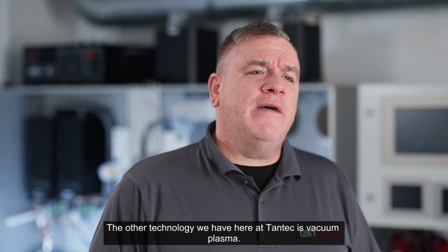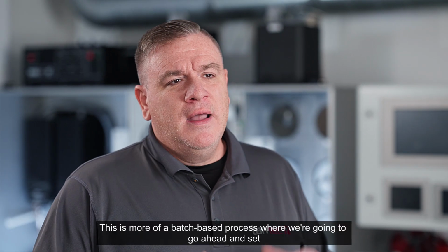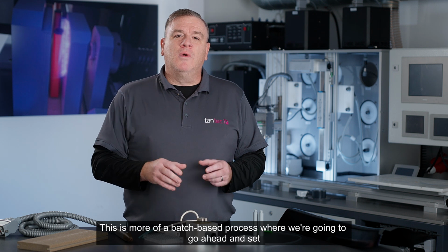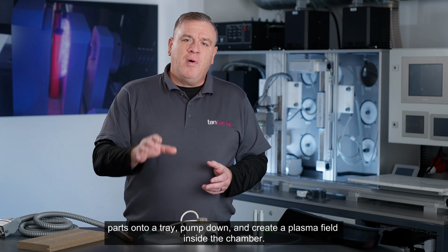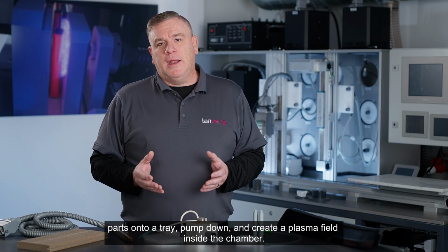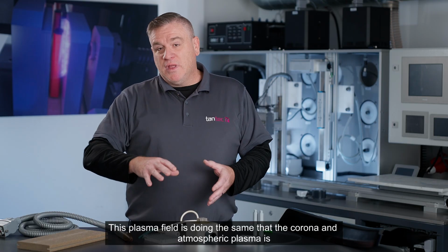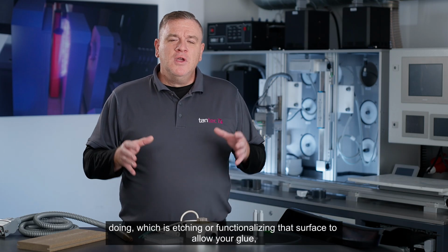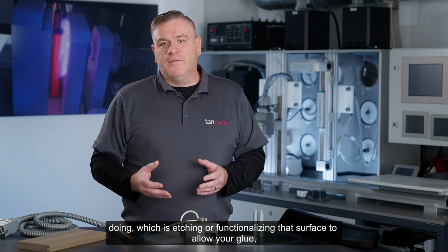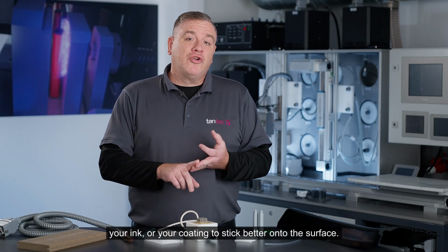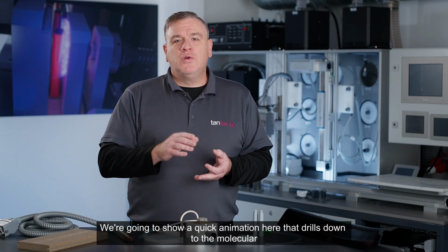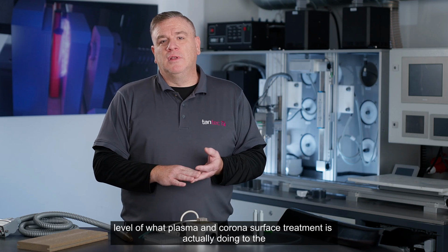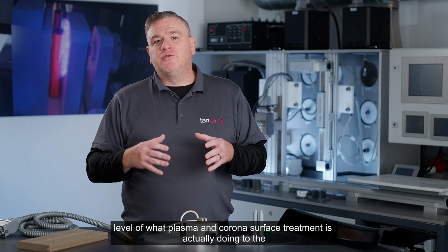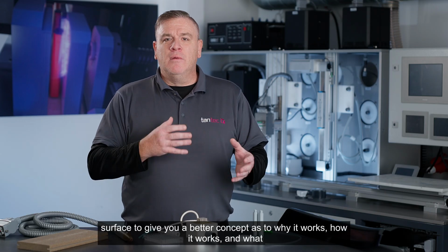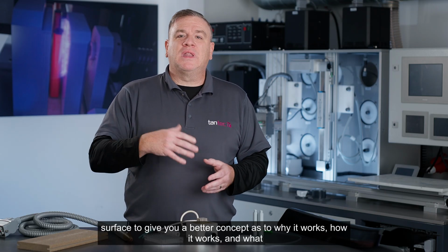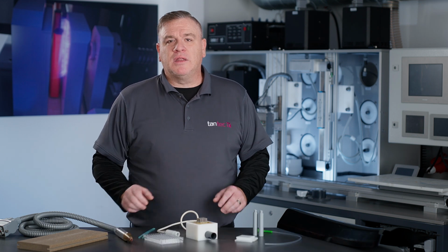The other technology we have here at Tantec is vacuum plasma. This is more of a batch-based process where we're going to set parts onto a tray, pump down, and create a plasma field inside the chamber. This plasma field is doing the same that the corona and atmospheric plasma is doing, which is etching or functionalizing that surface to allow your glue, your ink, or your coating to stick better onto the surface. We're going to show a quick animation here that drills down to the molecular level of what plasma and corona surface treatment is actually doing to the surface to give you a better concept as to why it works, how it works, and what to expect from the process.